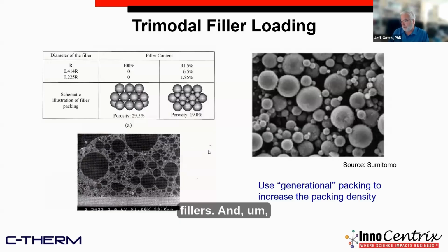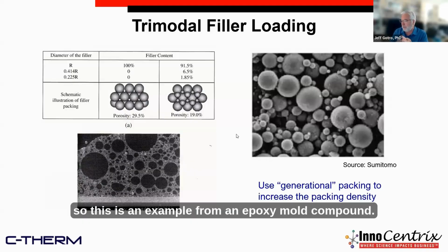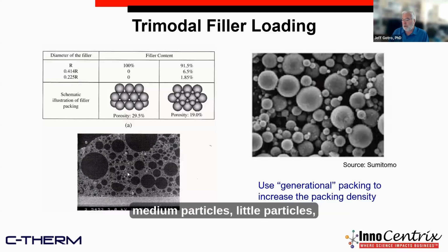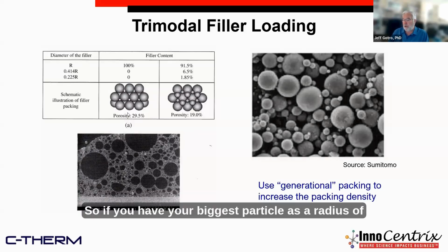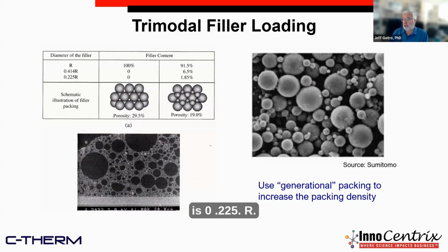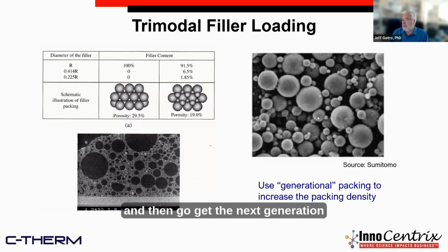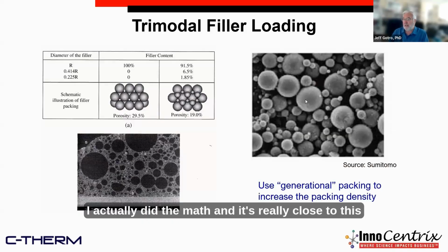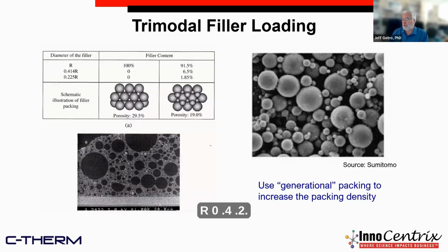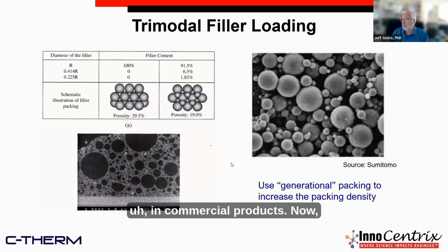Another way is to use trimodal fillers. This is an example from an epoxy mold compound, the black stuff that you see around the chips. You can see here there are big particles, medium particles, and little particles, and the mathematics has all been worked out. If your biggest particle has a radius of R, then the next generation down is going to be 0.41 times that radius, and the next generation down, the one that'll fit in here, is 0.225 R. So you can choose a big particle and then get the next generation and the next generation. I got this cross section and this SEM picture from the Sumitomo website. I actually did the math, and it's really close to 0.4, 0.2. So this is used in commercial products.